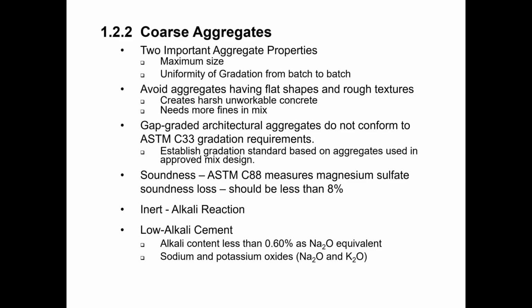So the maximum size of the aggregate can be a limiting factor on the design of the precast unit if we're using an aggregate that is relatively large in size. Another thing that we're concerned with is the uniformity of the gradation from batch to batch. Now, the coarse aggregate effect of variation in gradation is not as significant as far as how that effect shows up in the performance of our concrete mix. A concrete mix is very sensitive to changes in gradation of the sand, but not as sensitive to changes in the gradation of the coarse aggregate.